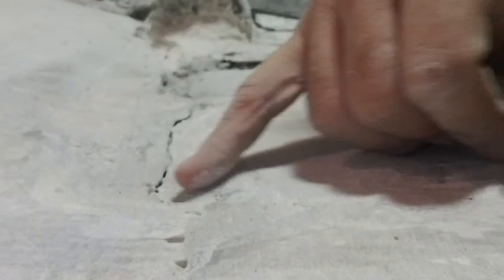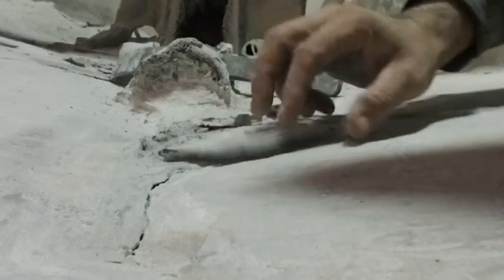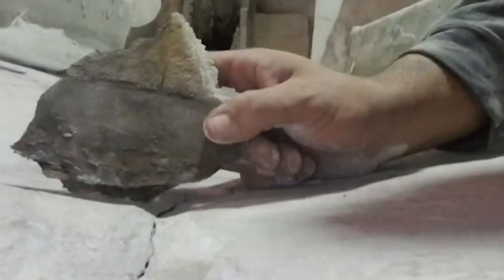There was an inch of Bondo and a half inch of surfboard glass, which actually, a half inch of surfboard glass is probably stronger than a half inch of the 24-ounce glass that I use, because there's so many more fibers per square inch because it's a finer mat. Doesn't matter though, because all the Bondo, check this out. Look at this fissure running all the way up. See that? So this piece, a little puzzle piece here, came out of right there. Look at that disaster. See, that's what I'm up against. See how it's all black there? Total delamination. It's ridiculous. But anyway, that is what it looks like if a grenade goes off underneath your boat.